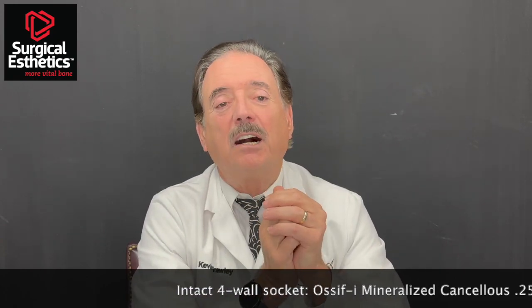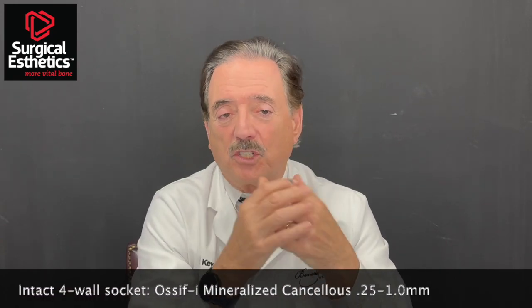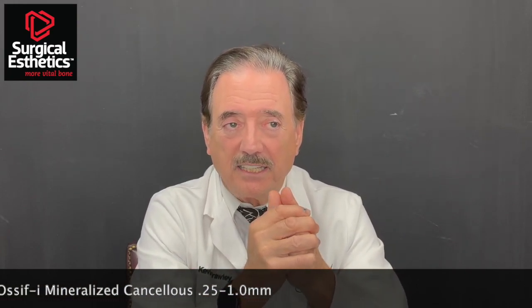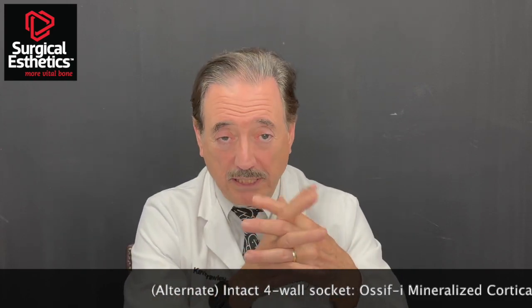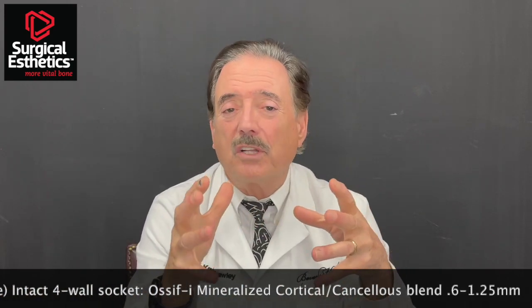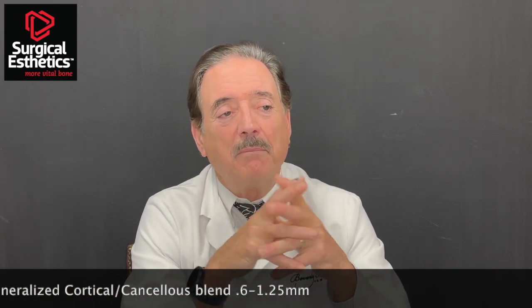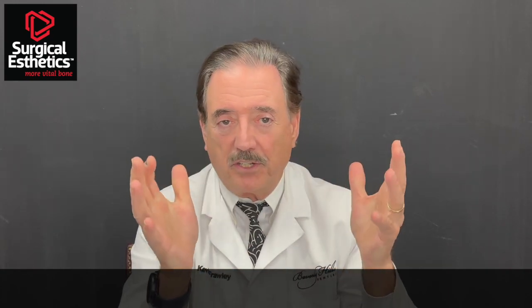If you have a single socket with no defects, 4 walls all intact, ideally what I would use is a straight mineralized cancellous because it will create a nice stable clot. It'll absorb blood. It'll turn over quickly. And in those situations, certainly right at 3 months, I'd go back and place the implant. You can also use cortico-cancellous in that area. I might give it a little bit more healing time if you're using a cortico-cancellous, but it certainly is appropriate as well.